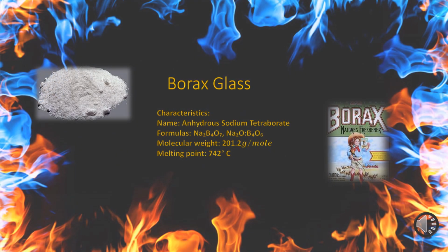Borax can be purchased in both states, one containing water molecules and the other without, commonly referred to as being anhydrous. You can purchase borax off the shelf at your local supermarket and drive the water off yourself in your oven, or you can purchase it from your chemical supplier as a higher grade of borax glass. Once the water of crystallization is removed, the resulting product can then be pulverized to a powder, resulting in the glassy borax glass.